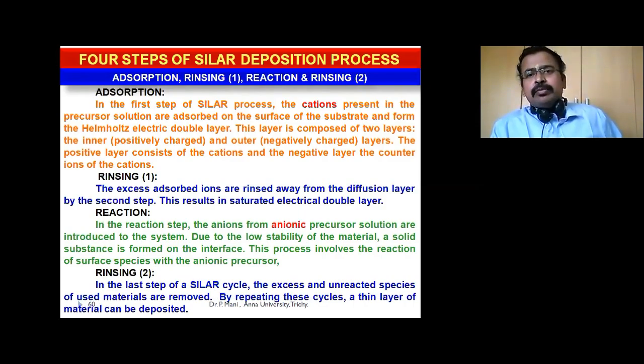This layer is composed of two layers: the inner, that is positively charged, and the outer is negatively charged. The positive layer consists of the cations and the negative layer the counter ions of the cations. The second process is rinsing. In the first rinsing, the excess adsorbed ions are rinsed away from the diffusion layer by the second step. This results in a saturated electrical double layer.